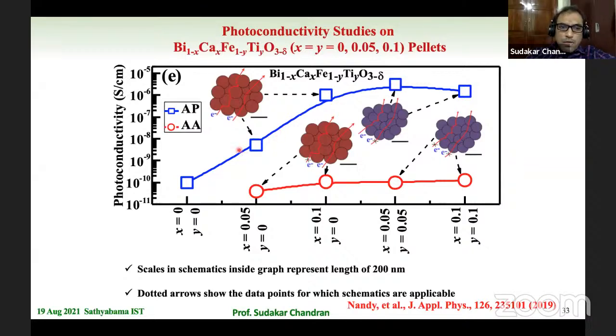For example, 3 to 4 orders of increase in photoconductivity can be obtained just by changing the composition. And of course, there is a different mechanism. The mechanism could be summarized into two different parts: the one that comes from the grain boundary region, where the defects are prevalent, and also from the bulk region, where, depending on the type of dopants you introduce, oxygen vacancies could come.